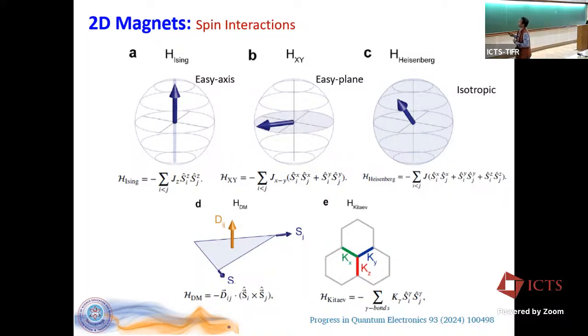But if there is an anisotropy, which is basically the easy-plane anisotropy, the spin can be in the plane, so it can have the x and y components. And this is the easy-axis anisotropy, where you can think of the Ising model giving us the understanding. And there are DM interactions and Kitaev interactions, which are also important players in 2D magnetic systems.